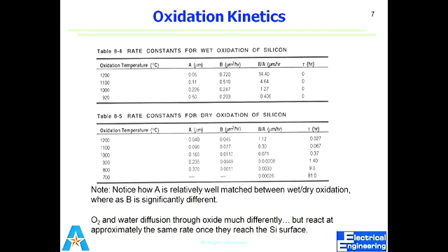So that's why if we have a thick layer, oxygen molecules cannot diffuse through, because in the case of a thick oxide layer, it's always a diffusion control process. Diffusion is the problem in the case of a thick oxide layer. Water molecules have a different diffusion as compared to oxygen molecules, so water molecules can diffuse easily, and the solid solubility of water molecules is also high. So the problem is with the diffusion. That's why wet oxidation is better in terms of growth rate as compared to dry oxidation.